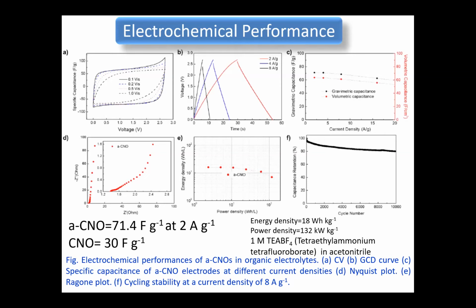Also, we have found the high conductivity of carbon nano-onions, as we can see in graph D, the impedance data, which shows a very small or negligible semicircle in the high frequency region, and the extending long tail shows high capacitance. Also, these activated carbon nano-onions show a high energy density of 18 watt-hour per kg with a power density of 132 kilowatt per kg, and this device shows a high cyclic retention of 80%. Thank you. So that's all from my presentation.